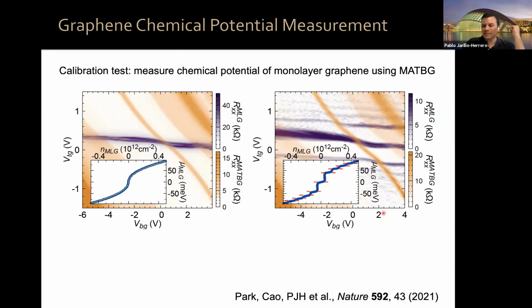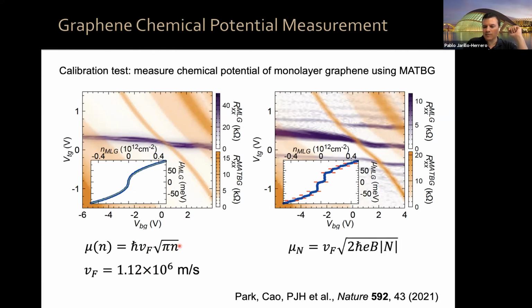If we do this in a magnetic field, this will give us the chemical potential in a magnetic field. And indeed, you can see that there is, I don't know if you can see it because it's so perfectly on top, a white line on top here. This is just the chemical potential of monolayer graphene where we fit the Fermi velocity and we find a Fermi velocity of 1.12 times 10 to the 6, which is exactly the Fermi velocity of graphene. And you can see that it exhibits this Dirac behavior, square root behavior here in density. The same thing in the presence of a magnetic field, we have this ħv_F times square root of magnetic field and Landau level index. So this technique works very well.